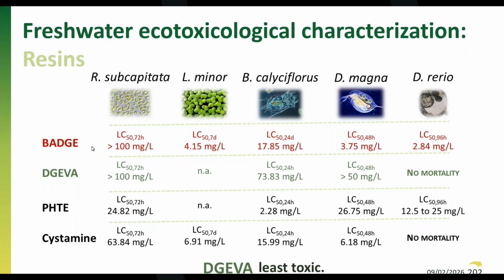BADGE is a bisphenol-based resin, so it's not bio-based. And then we have here DGEVA, the PHT and cystamine that are bio-based resins. And here I included the values of LC50. This is the concentration of the resin that causes 50% of effect in each one of these organisms.